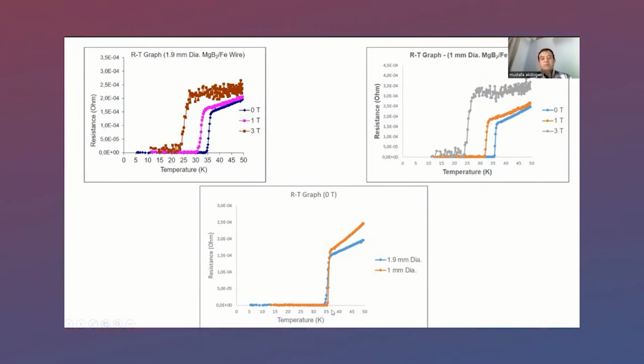So as we mentioned inside the topic, if we apply heat treatment on our samples with a tube furnace, it may take 6 hours to reach this kind of behavior. But if we apply induction heating on our wires, actually it takes only 1 minute, and power consumption is nearly equal to 90 watts. So there are huge differences between them, and this will be beneficial for industrial application. Thank you for your attention.